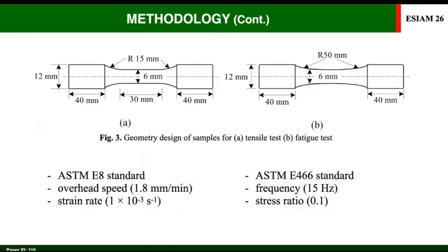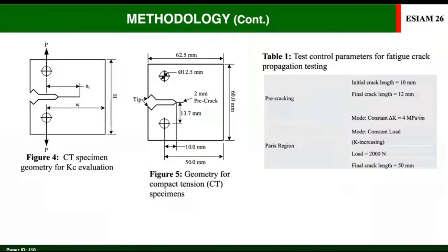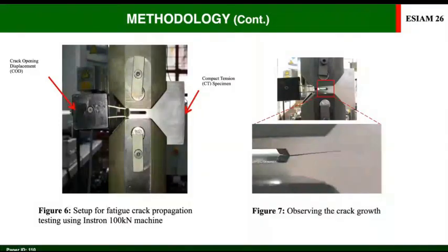Figure 3 shows the dimensions of the tensile and fatigue test specimen according to ASTM. Figures 4 and 5 show the geometry of the compact tension CT specimen with the dimensions as in Table 1. Figures 6 and 7 show the setup of a CT specimen on the Instron machine. The evaluation of the critical stress intensity factor KC is carried out. The test is performed in two stages. First is the pre-cracking. Second is the Paris region, conducted using a servo-hydraulic fatigue test machine, while the crack opening displacement COD gauge is attached to the knife edges at the specimen.